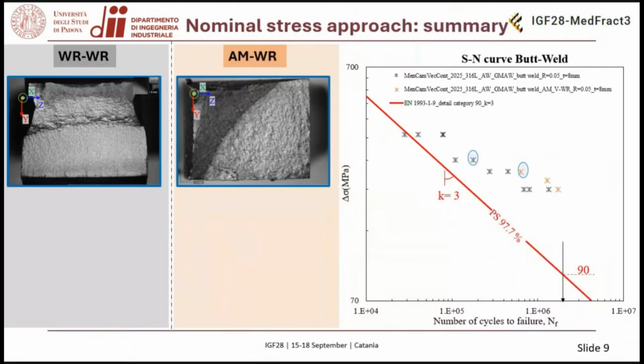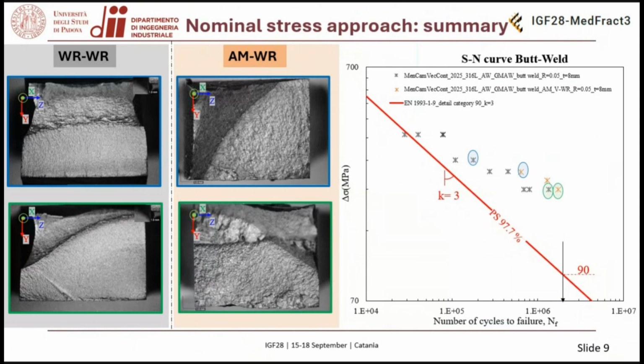So comparing wrought and additive welded joints for a high-level condition, we observe the main difference is in terms of the different roughness of the surfaces. Here we have multiple fatigue crack initiation points. On the contrary, here we have one main starting point. Focusing on low-level test specimens, also in this case we have different roughness. Here we have one main fatigue crack initiation point and only limited secondary starting points, while here we have only one fatigue crack initiation point.